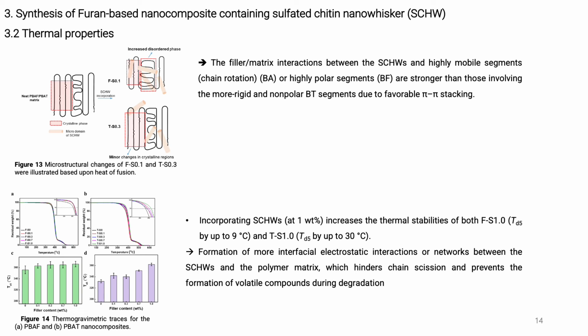These results indicate that filler-matrix interactions between the filler and highly mobile segments like BA, or highly polar segments like BF, are stronger than those involving the more rigid and non-polar BT segment, due to favorable pi-pi stacking. Here we illustrated the microstructure changes in FS0.1 and TS0.3 based on the changes in heat of fusion.